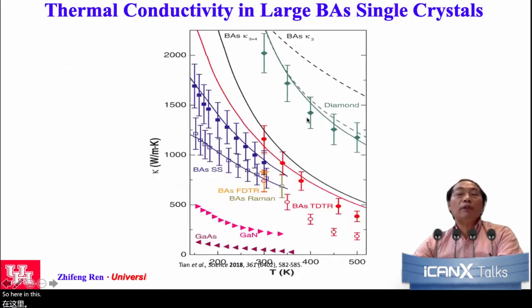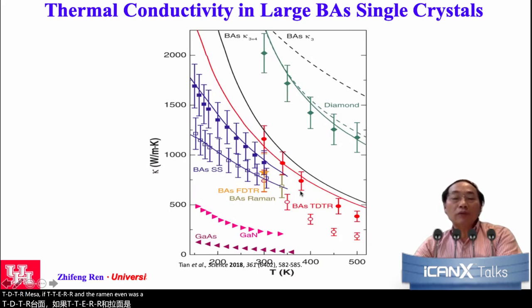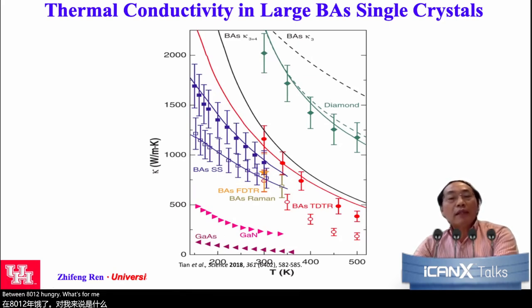So here is a summary of the thermal conductivity measured by different ways: TDTR, FDTR, and Raman, and also transport. We found boron arsenide at room temperature has a thermal conductivity somewhere between 1,000 and 1,200 watts per meter per kelvin. It's not over 2,000 yet, but at that time it was much higher than the numbers of other materials, which is very exciting and made us further improve the growth.